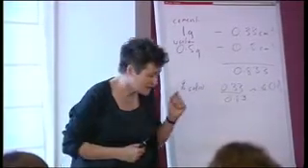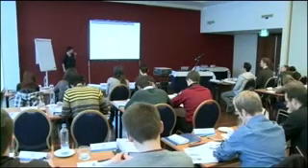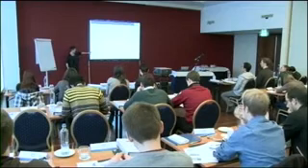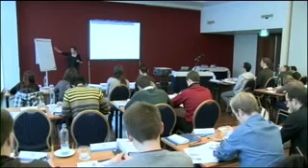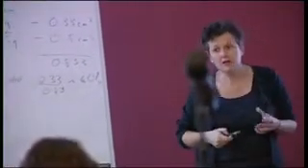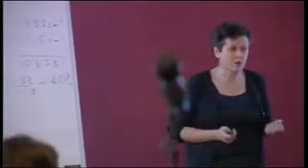Okay? Now, the second point, which is equally important and really concerns what happens at the end, is what it says down at the bottom here. What I'm telling you is that this cement, when it reacts with water, just about doubles in volume. So if I start with 40%, what do I end up with?